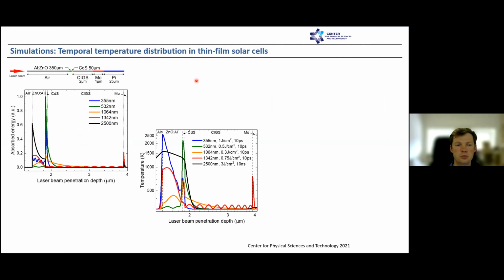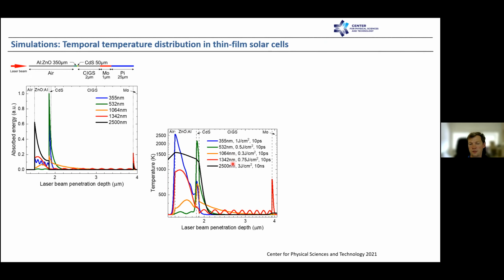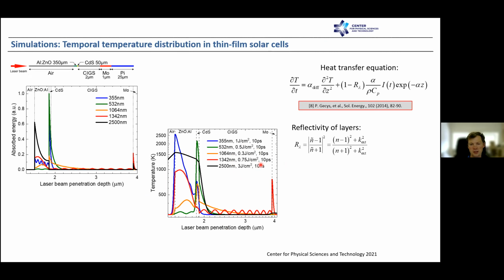Of course, we also did some simulations of how these different wavelengths interact with multi-layer structures. This is the laser absorption and calculated temperature distribution inside the thin film structure. We see that most of the temperature or absorption is at the top layers or top contact layers. However, we see some diffusion of heat into the CIGS as well, mainly with infrared, 1064 and 1342 nanometer wavelengths. You even have a temperature spike at the interface between the molybdenum and CIGS layer for 1342 nanometer wavelength. So some of the wavelengths might affect the CIGS layer more than others.